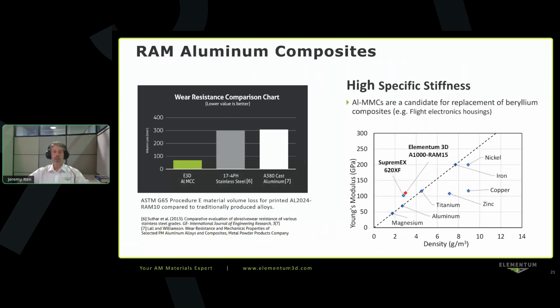So looking at RAM aluminum composites a little bit further, you can see that they also benefit greatly in wear resistance. On the left is one of our aluminum metal matrix composites. In this case, it's a RAM 10 2024 based aluminum alloy. And the bar chart there is the amount of material that's lost due to wear in the equivalent test for each of those three materials. So the aluminum alloy bar being the smallest means that it lost the lowest amount of material, which is good. The 17-4 precipitation hardened stainless steel, you can see lost over 3 times the volume in the equivalent test. And an A380 cast aluminum alloy is also shown there for comparison, also showing much higher wear than the composite material.